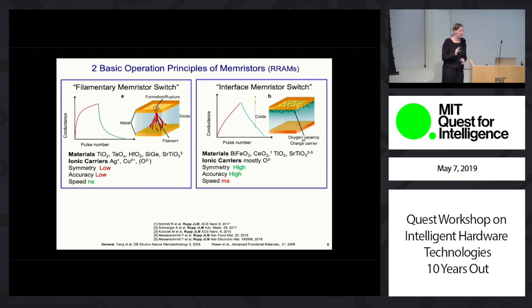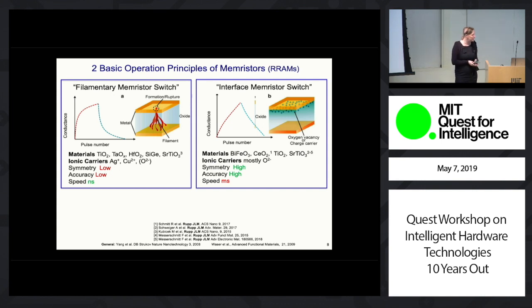It's just showing the opportunity that it could be either asymmetric or symmetric, depending on the operation you later want to take. My point here is that currently, with materials, it's very difficult: you would end up on one side or the other, and you can make careful decisions on a hardware level. What's interesting on the example of lithium titanate is that you could later, by lithiation in the three-terminal architecture, even decide whether you want it here or more here. If I want to do that in strontium titanium oxide, you can to some extent, if you operate it in a different regime. That's also what we published, by field strength or by sweep rate or pulse rate. But we're still within certain limitations.